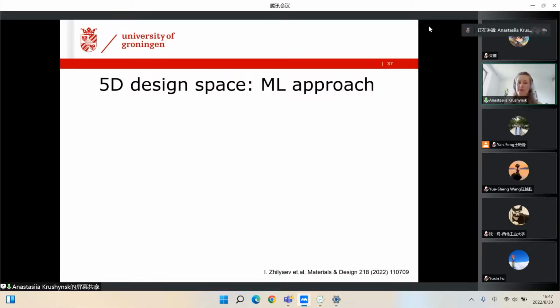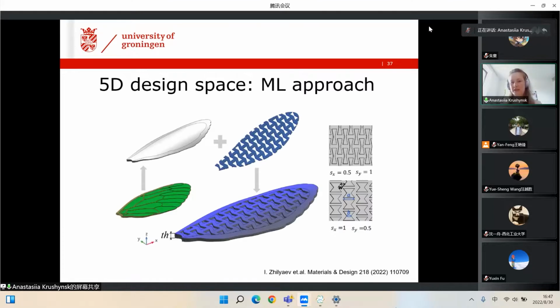So having 5 parameters to describe the wing pattern, we have 5-dimensional design space. To explore it, we use the machine learning techniques. So first, we extended the design to include auxetic structures too, thinking that maybe auxetic material behavior will be beneficial for flight. And also, as you can see, it's anisotropic, and we saw that some optimized designs have anisotropy along the y direction. And with this extended space, we again apply this multi-parameter optimization procedure in the 2 steps, but for each step now we use the machine learning approach.